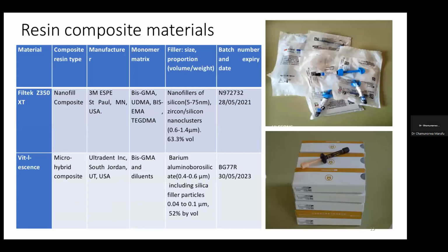So the resin composite materials which I evaluated were Filtek Z350 XT, which is a nanofill composite from 3M, and Vit-l-escence, which is a micro hybrid composite from Ultradent. The monomer matrix for these two seems to be similar. The difference though being the content of the resin versus the filler. For the nano composite, the filler was 63.3% by volume, and for the micro hybrid, the filler was 52% by volume.